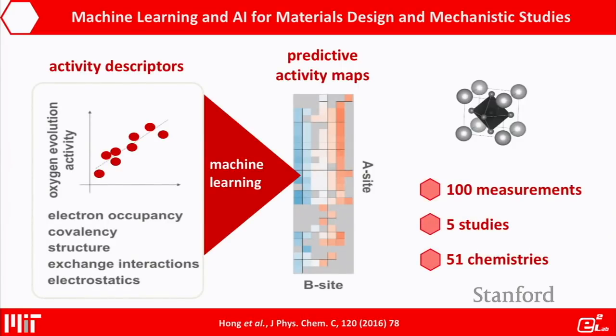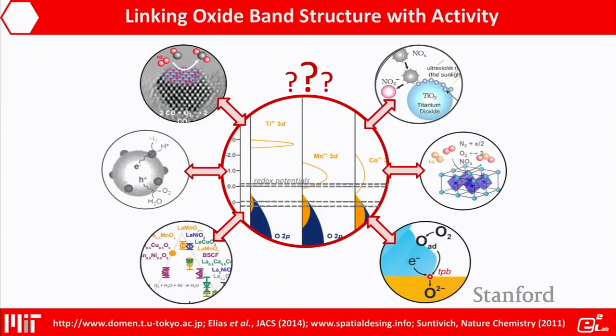So we mentioned that metal-oxygen covalency can play an important role. It appears to be a dominant parameter in our studies. If you look at the literature over the past 50 years, you find maybe 30 different parameters or descriptors proposed for oxygen evolution activity. Then we carried out a very simple machine learning study on 100 measurements, and what we find is that only two parameters play a very important role: metal-oxygen covalency and having the eg filling of the transition metal near 1. Both parameters correlate most strongly with the oxygen evolution activities.